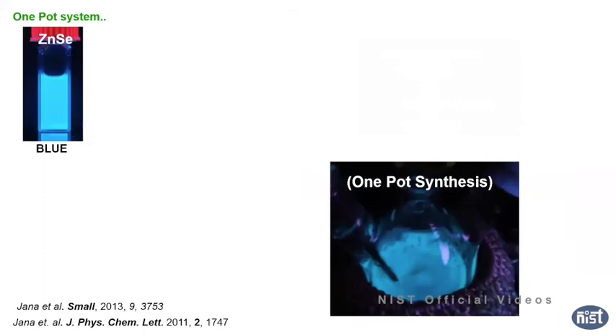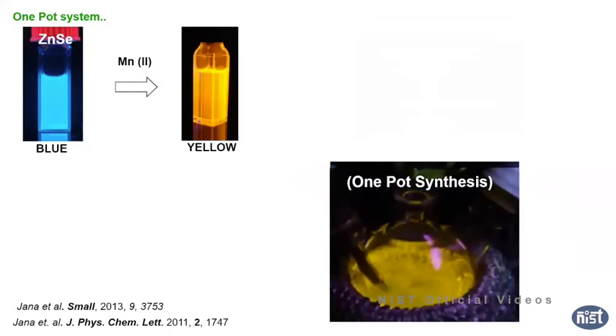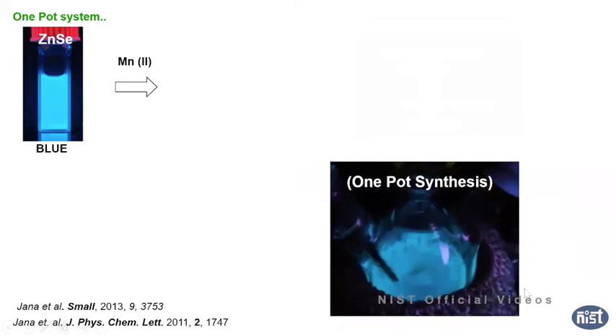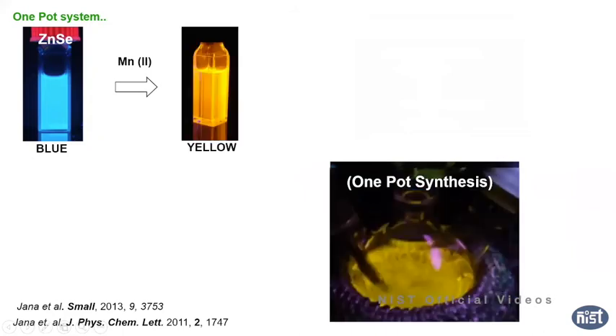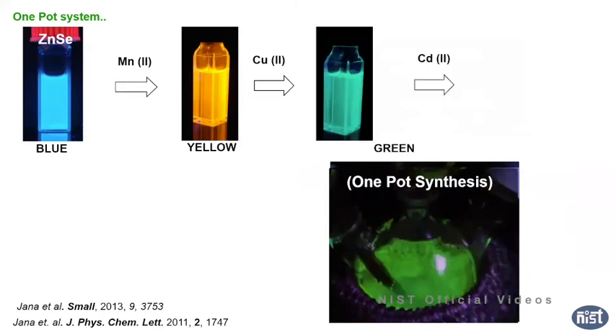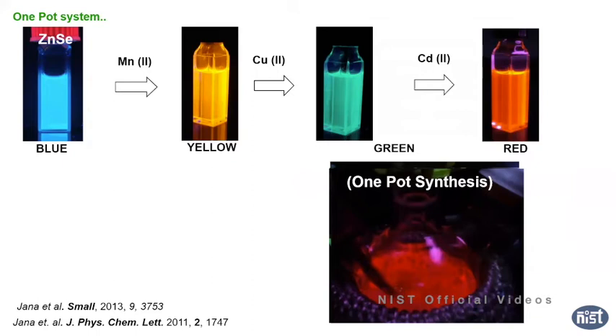So you can see that in only one pot synthesis, you can start from the blue emission, and by just putting in a different ion, you will have a different color of emission. Previously it is only zinc selenide. You put manganese, you will have a yellow emission. Then you put copper, again you will have green emission, and you put cadmium, you will have red emission. So interesting, just in one pot, you can change to any different emission by just adding a different kind of cation into the solution. You do not need to change anything else, and the particle size will not change.